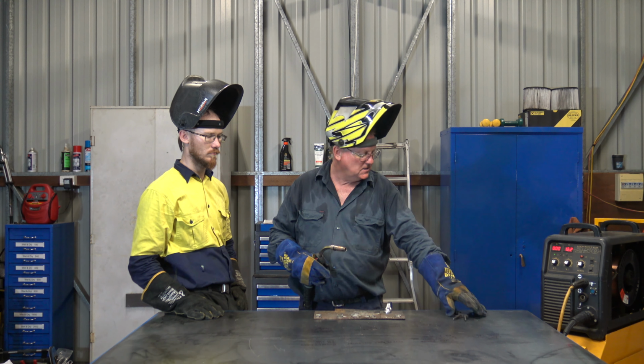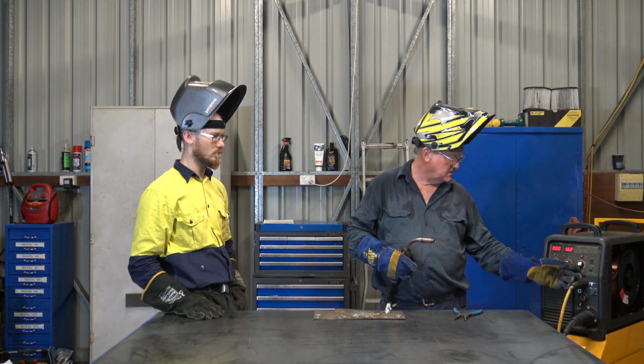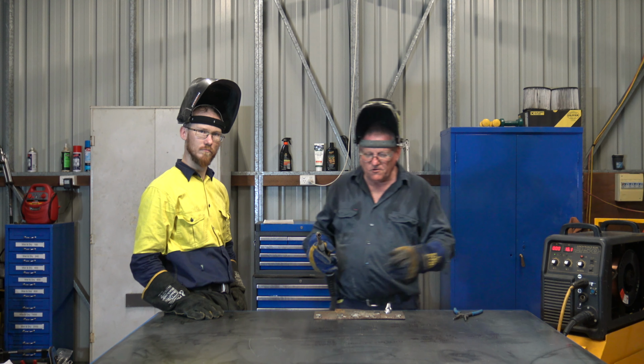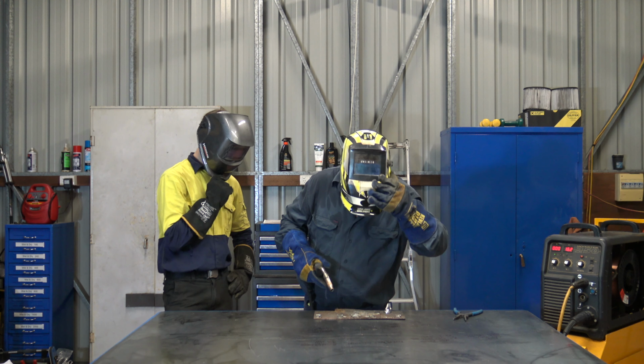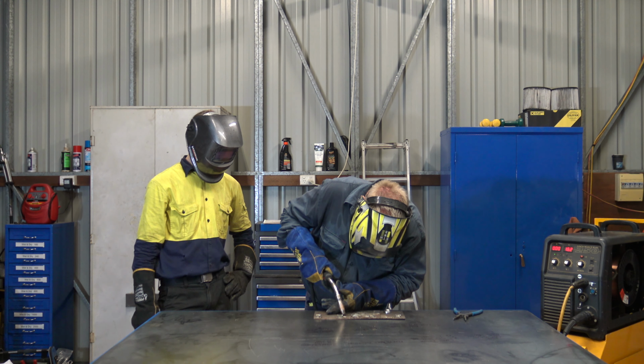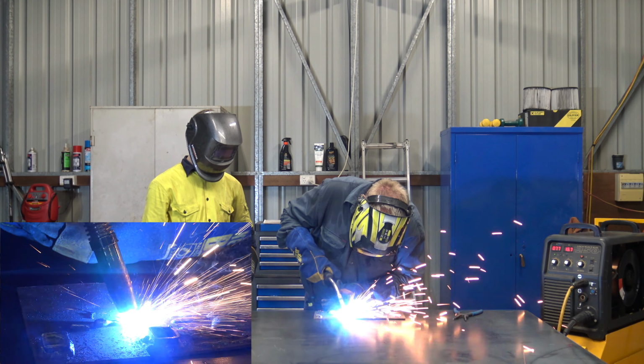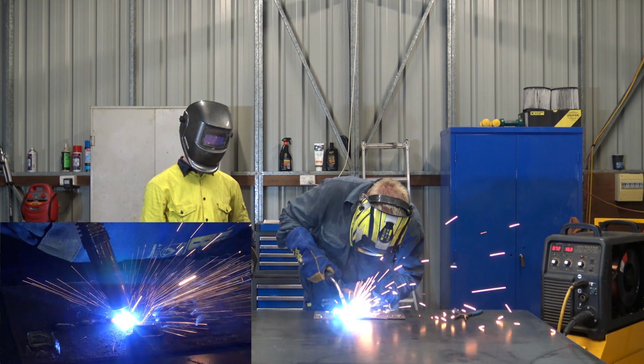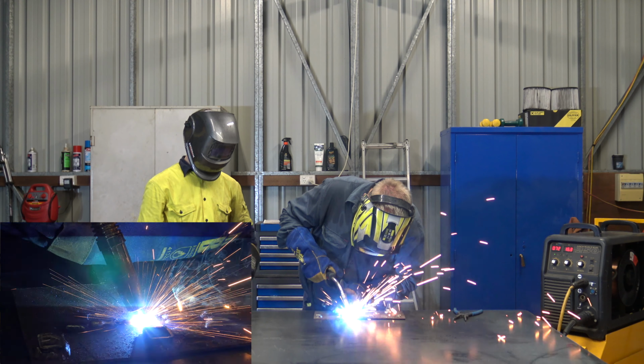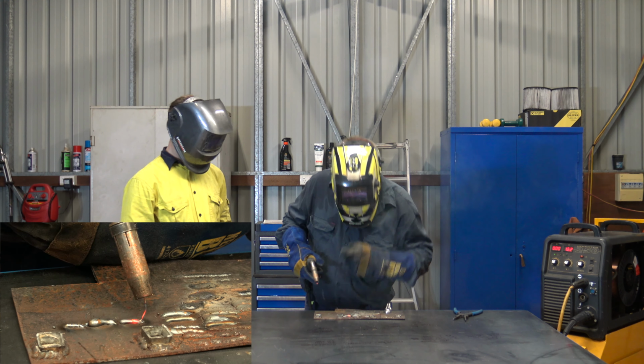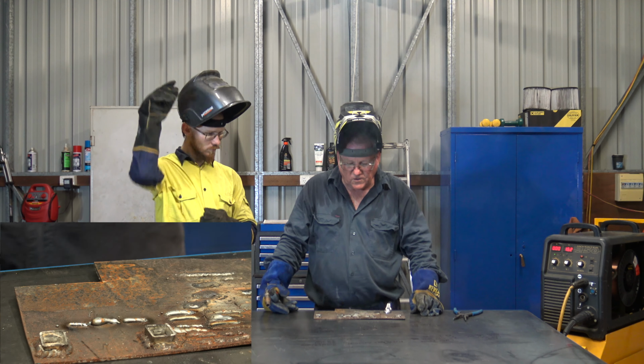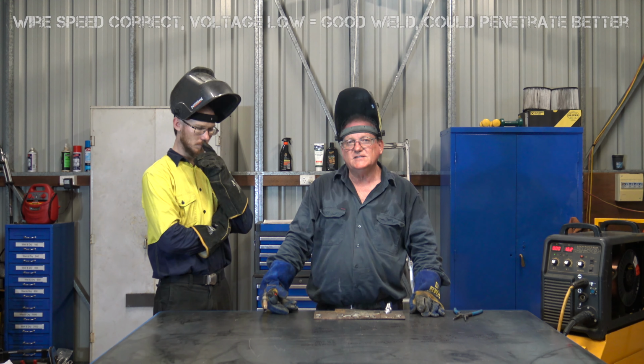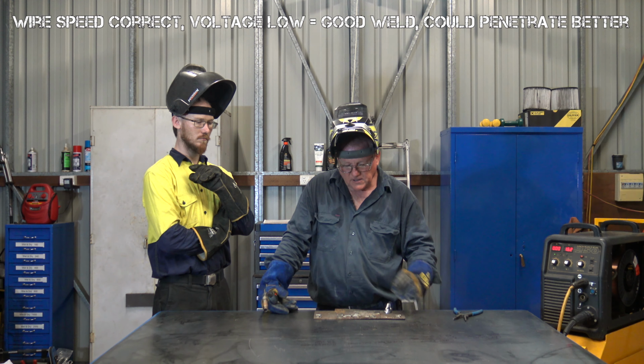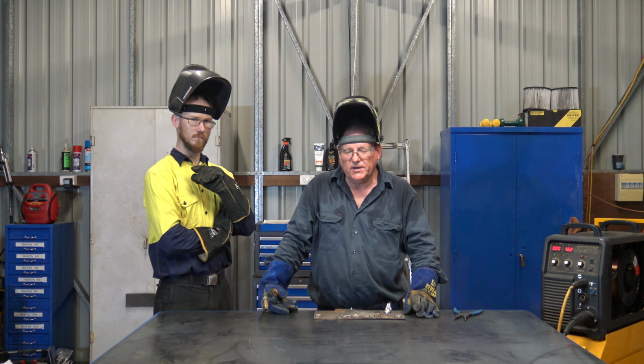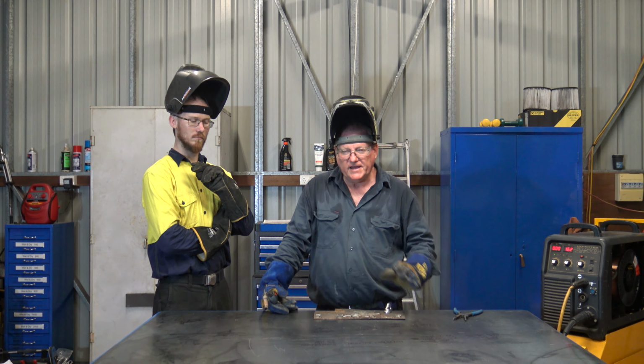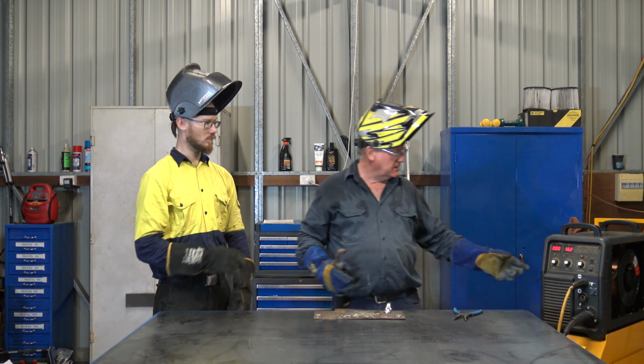So now we'll adjust the wire speed to somewhere that should be about right, and then we'll take a look at the weld and see what needs adjusting. So that's more the sound we're looking for. We have a nice weld, but it's still a little bit lumpy, still a bit high, although it is actually welded into the plate and biting in. So if we want to flatten that weld out and make it look a little better, we can increase the voltage somewhat.